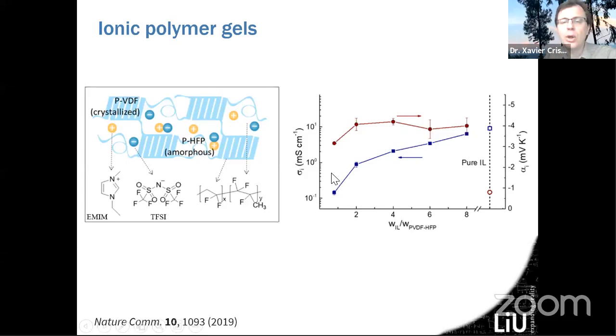Then we can look a little bit at the ionic conductivity, shown here in the blue curve, as we add more and more ionic liquid. When we start to add ionic liquid here, the ionic conductivity increases. Just for comparison, you can look at the value of ionic conductivity for the pure ionic liquid, and you see that we are quite close to that value, meaning these polymeric gels are full of ionic liquid and are conducting the ions quite well.